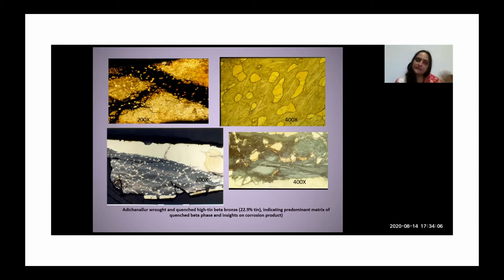Or rather, it has transformed into tin oxide. That's what you see, this opaque gray material, which is all tin oxide. So it has all formed tin oxide compounds. And that's the kind of corrosion that has happened in this case.